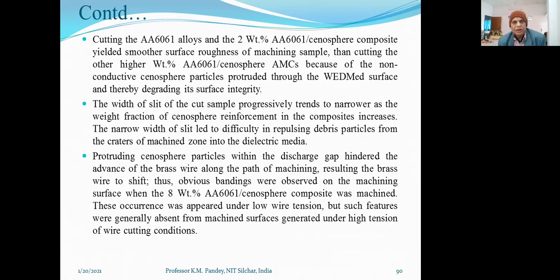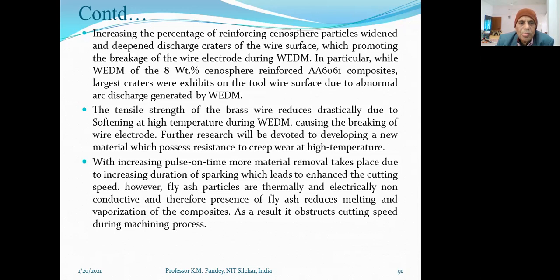Protruding cenosphere particles within the discharge gap hindered the advance of the brass wire along the path of machining, causing the brass wire to shift. Thus, obvious bandings were observed on the machining surface when the 8% by weight AA6061 cenosphere composite was machined. This occurrence appeared under low wire tension, but such features were generally absent from machine surfaces generated under high tension of wire cutting conditions.